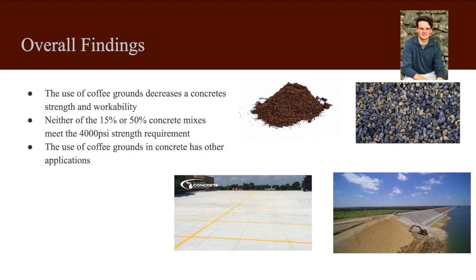However, this does not mean that there are not viable applications for use of coffee grounds in concrete. If we had more time and resources, we would have tested lower percentages of coffee grounds in the concrete to see how that affects the strength. Particularly in the 5 to 10% coffee grounds percentage range, because there is research out there that shows that the optimum amount of coffee grounds to use is between 5 and 10%. This is because this uses the most amount of coffee while mitigating the amount of strength loss.